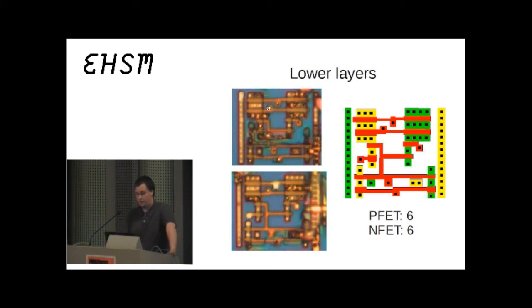Basically, this follows through. You can see a lot of the contacts. Some of this right here is some of M1, the metal, that didn't get completely etched off. You can kind of ignore that, or you can look at the higher level pictures to figure out which components you need to ignore. And that's one of the big things, that there's a lot of sample preparation involved, so it can really make or break a project depending on how good of images you're able to acquire from the sample preparation.